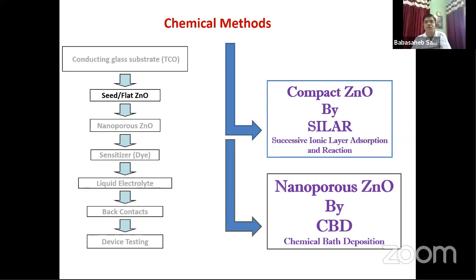There are two types of zinc oxide we have used. One is called compact or seeded zinc oxide, which is used as a blocking layer, because in this type of solar cell we are using a liquid electrolyte, and this liquid electrolyte can have contact with the FTO coated glass substrate, and your device can get shorted, because you have porous zinc oxide with a very high surface area. In order to avoid this, we have used a compact or seeded zinc oxide by using the simple SILAR method.